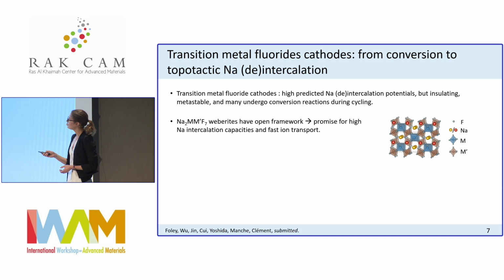But one of the interesting transition metal fluoride crystal structures is the Weberite crystal structure. This particular crystal structure is of interest because it has an open framework, so you've got these kind of tunnels where you could imagine that sodium can diffuse through the tunnels, be extracted and reinserted reversibly. And so there is some promise for high sodium intercalation capacities as well as fast ion transport.